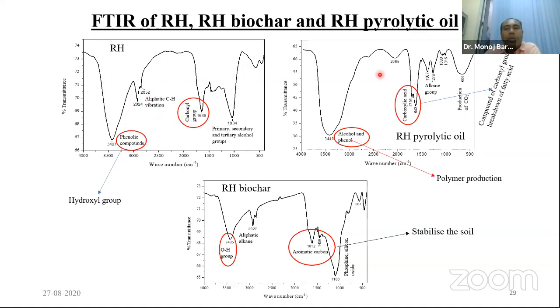But when this biomass is converted into products such as the liquid products, and if we do the FTIR analysis, then we can see some different types of properties. Here also, of course, we get one peak, but this peak is not that much observed. So that means we can understand that in the liquid sample also hydroxyl kind of group is there, which indicates the presence of alcohol and phenolic group, but it is somewhat lower than the biomass sample. So this indicates that during the pyrolysis, when it is converted to liquid product, some oxygenated compound actually is converted into some other kind of compounds, maybe carboxylated compounds.